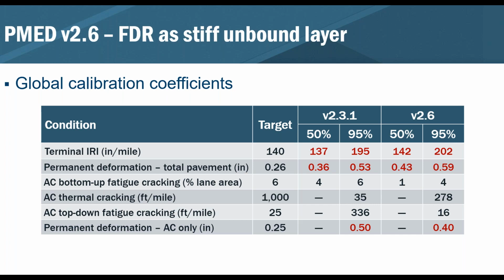Top-down fatigue cracking actually also reduced pretty substantially from version 2.3. So I found that interesting as well. Now the interesting part too is looking at the bottom-up fatigue cracking, and so we're going back to saying, well, why did PMED predict a higher level of fatigue cracking than what is actually being measured. If you look at the 50% reliability value from version 2.6, it's probably tracking pretty well. So that's also an interesting thing, that the difference between 50% reliability and 95% reliability certainly can have an impact on the differences that we were seeing. So I guess that's another food for thought, if anything.